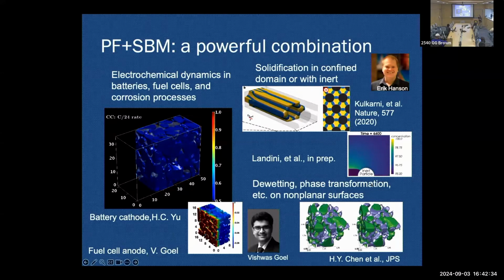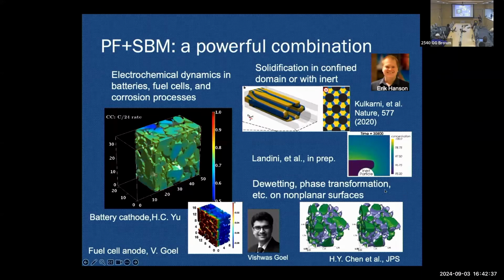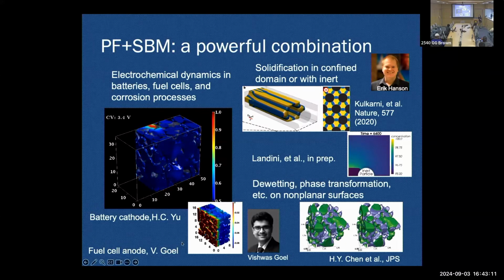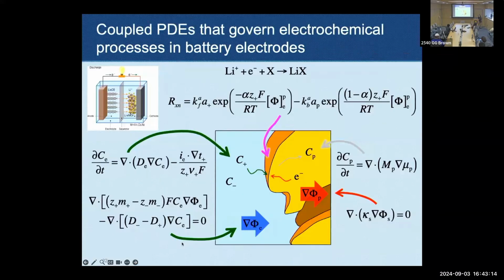You can also look at the growth of a particle, the growth of a precipitate when there's an obstacle particle that's trapped, so it's going to have to go around. You can also study dewetting, and this is dewetting in a complex microstructure. It's nickel dewetting YSZ, depending on the hydrogen partial pressure that changes the interface relation. So these are a couple of examples, but I'm going to talk about this one. What does it look like?